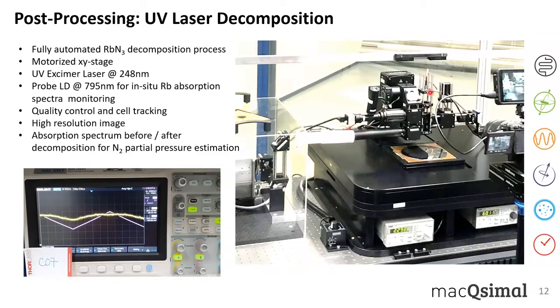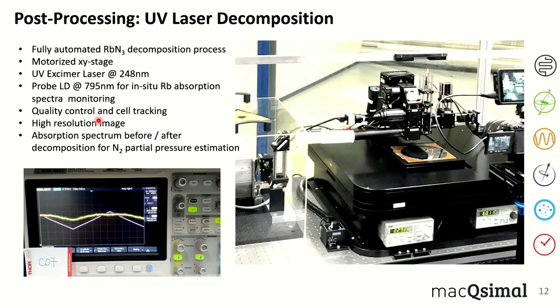In this setup, we also have a high-resolution camera which takes a picture of every cell. And with this absorption spectra, that I unfortunately can't show now, we can even have a first impression if the cell is good or if maybe there's a leak problem, because from the width of the spectral lines, we can conclude the nitrogen pressure inside the cell, so we know also if the decomposition is already 100% or only part of it.